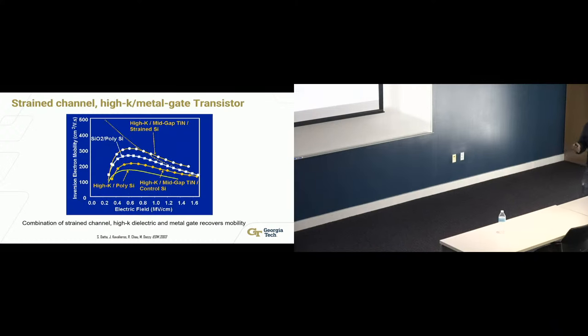After that, when we did these experiments, when we first went from silicon dioxide polysilicon to high-K polysilicon, we saw a huge drop in electron mobility. These are measured: you build the transistors, measure, and extract the mobility. But then when we switched from polysilicon to mid-gap titanium nitride, ultimately we didn't use mid-gap work function titanium nitride, but that's a different story.